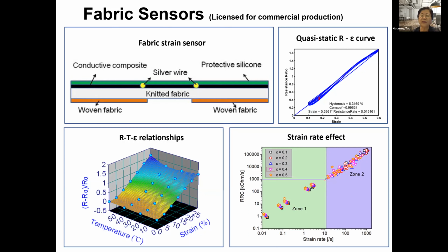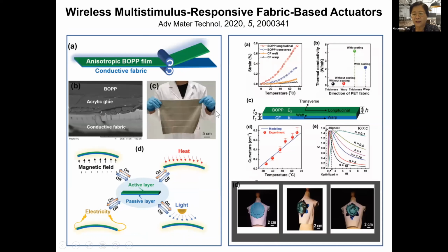And it also has a very nice dynamic response. In the picture here on the right side, this part shows the strain rate effect spanning several decades. And you can see the response is almost linear. This calibration curve can give us very good application in anything involving impact in dynamic situations. Now, that sensor example has been used by industry and is commercially produced.